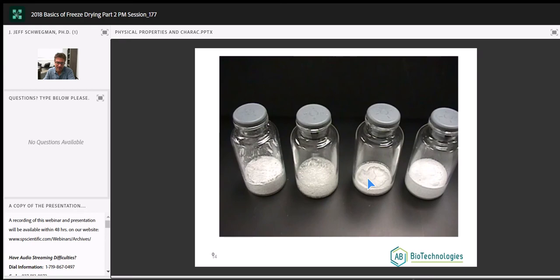Sometimes it'll manifest itself as a ring, a dissolved ring of material on the bottom of the vial. This one shows bubbles. Now, this is a rigid, hard solid, but it's got these bubbles entrapped inside of it. This was drying at a temperature above the glass transition temperature. So like I mentioned, ice was still present, holding up the structure. The interstitial space was a fluid.